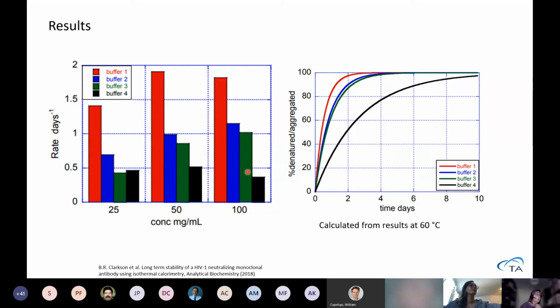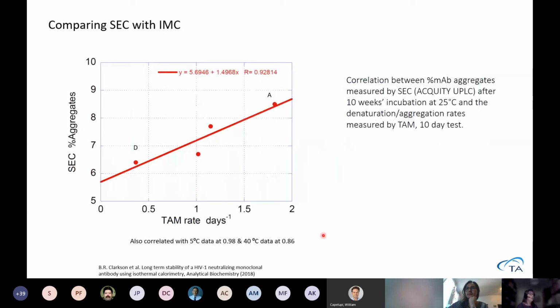If we know the reaction rate for how quickly it aggregates, we can also calculate how long it takes for the protein to aggregate at these measured temperatures for the different types of buffers. We can see there is a difference between the buffer compositions. This can then be compared with the size exclusion chromatography, where you put the percentage of aggregate versus the rate, and we can see we have a correlation and the same ranking of the different buffers in this graph.